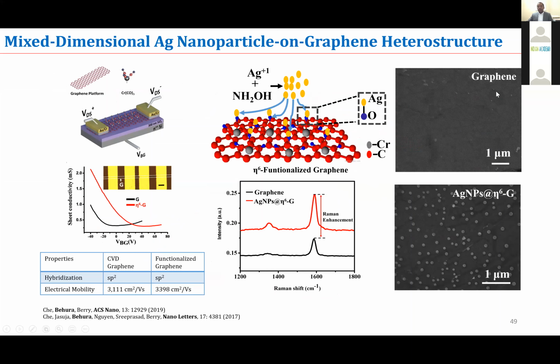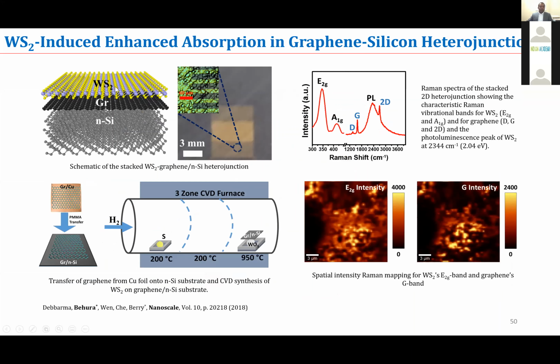It is difficult to anchor or decorate graphene with the nanoparticles on top without any functionalization. And then another type of structure where we have a two-dimensional semiconductor, which is tungsten disulfide, placed on graphene, and both these heterostructures are placed on silicon, and this combined hybrid structure was synthesized again using a CVD process that I discussed.